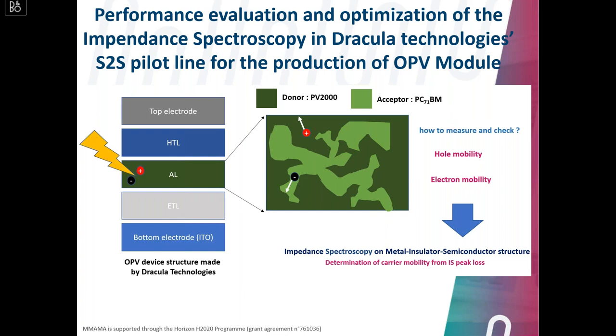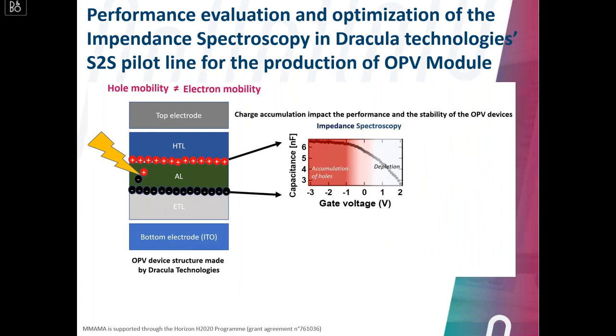For that, MATERIA NOVA especially developed a device structure which is compatible with our materials in order to determine all these parameters, the hole and the electron mobilities, based on what is called the metal insulator semiconductor structure. With this technique, we are able to determine the carrier mobility of our active layer. An important point is that, in general, we can observe some specific behavior with our device structure, like the S shape, for example, which is an indication that we have some problem.